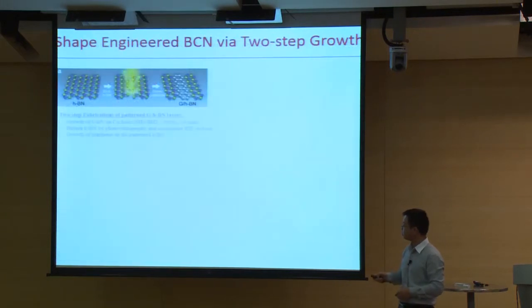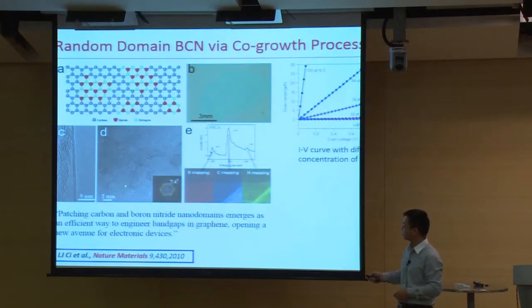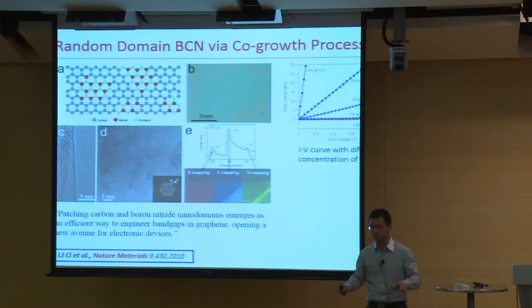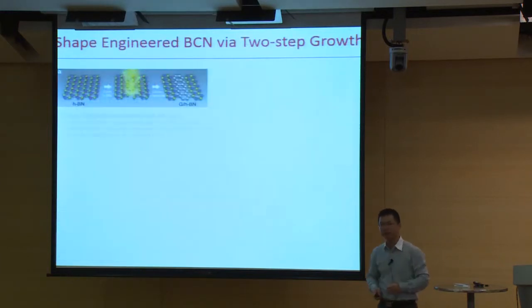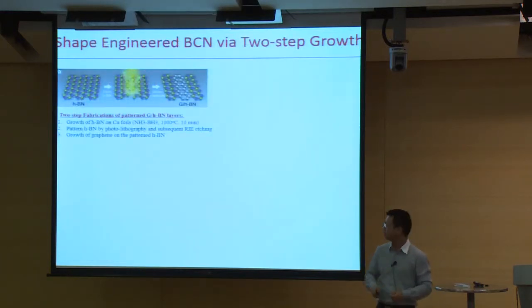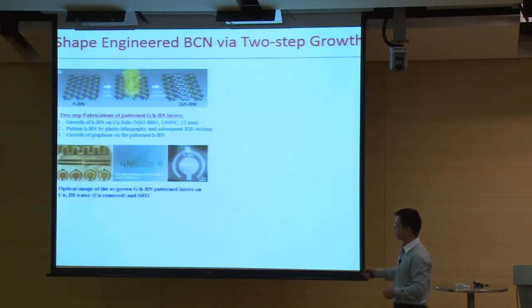And the problem is that for this material, the boron nitride and graphene domains are randomly distributed. So we are thinking, can we control the domains of graphene and boron nitride? The way we did it is, first, we grow the boron nitride, and then we etch part of the boron nitride, and then we regrow the graphene in the etched areas, so we can get planar graphene-boron nitride hybrid structures.